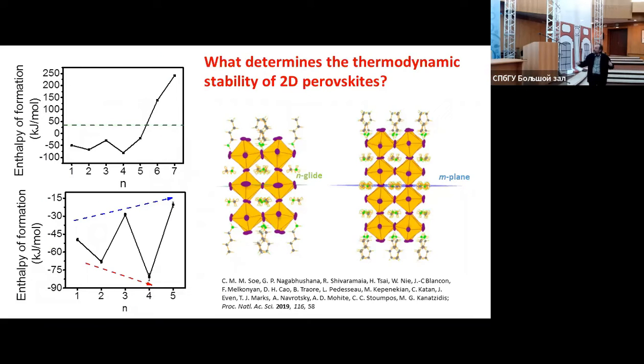Another interesting work we did with Alexander Navrotsky and Santiago was the thermochemistry, and we found that the enthalpy of formation differs depending on whether the number of inorganic layers is odd or even. For this particular set of butylammonium perovskites, it's much more stable to stabilize n equals 2 and 4 layers, as opposed to 3 and 5. Ignore this part, this is probably a wrong measurement. You cannot go above the formation enthalpy of the 3-dimensional perovskite.